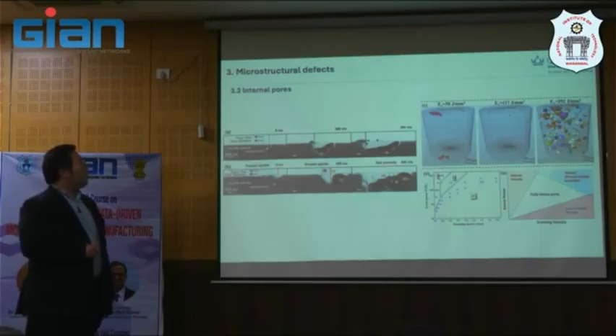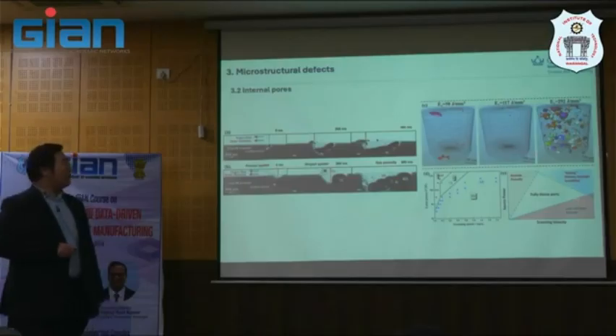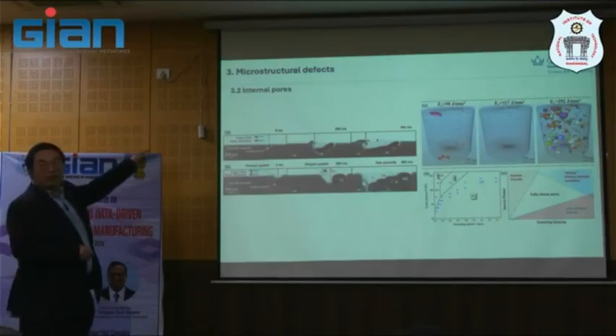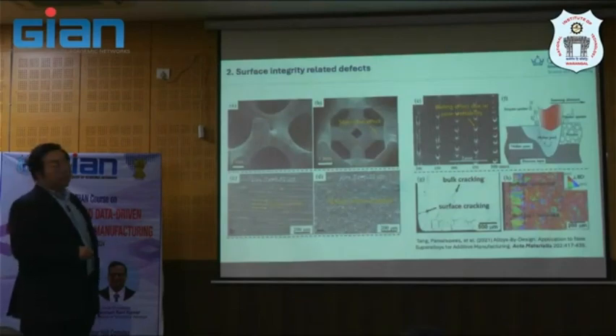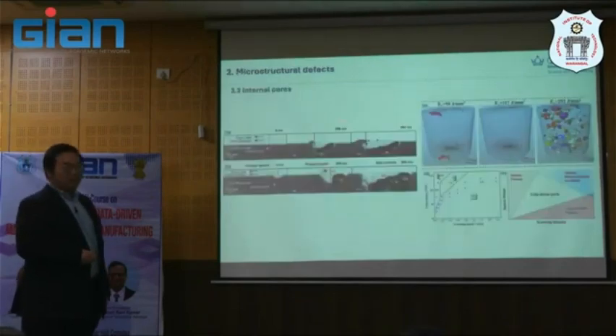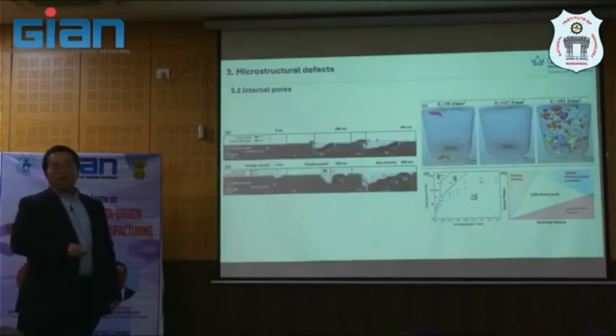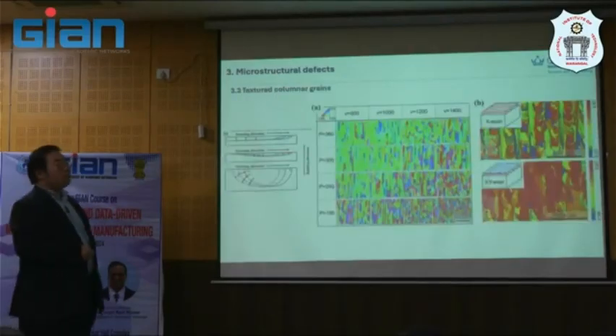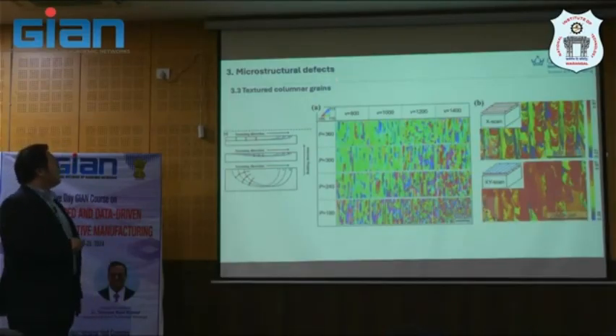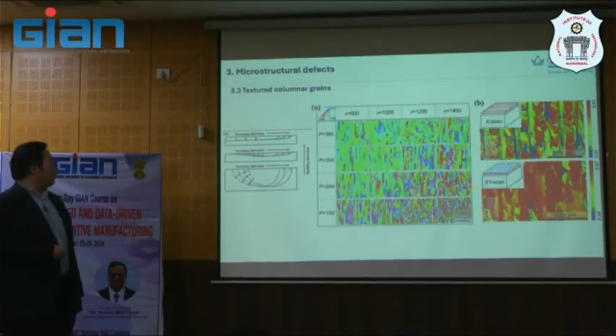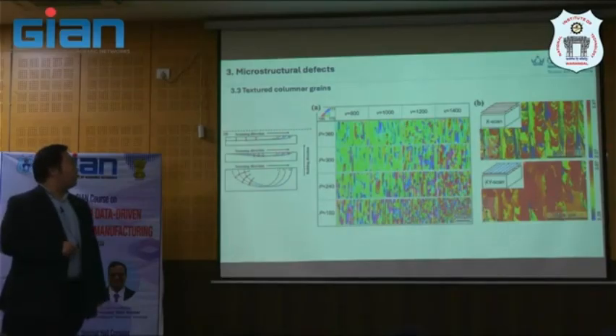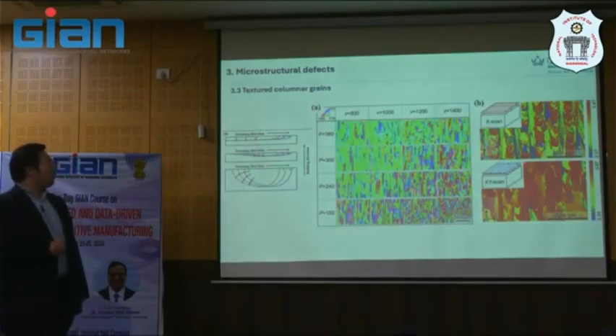A balling effect when you have very high velocity and high power, and then that balling effect takes place. Again, the balling, we put it in the last slide on surface integrity. But anyway, it is related to this P and V. Everything originated from here. So the next one is the microstructure defect, which is texture, columnar grains. It's one of the microstructure defects. So you will see this diagram clearly when you use P and V here. You will see the microstructure change quite significantly. At some conditions, let's compare here and here.